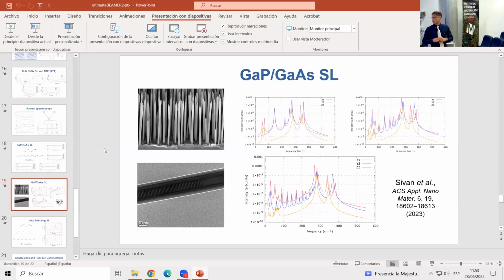And what about the intensity of the Raman peaks? The intensity of the Raman peaks, I guess that I sort of cheated, meaning that we can only assess that afterwards. So only after having computed the spectrum, we observe that actually in the twinning superlattice case, the superlattice structure only affected the Raman spectra in a minor way. Because in principle, of course, you will expect a more homogeneous electronic density along the lattice, because basically electrons are facing the same amount of charge in the nuclei. But electrons are so strange and quantum and unpredictable that you can only assess what is going to happen once you have computed the full wave function, whatever the approximation you use, and you have computed the full electro-optical response of the system for the twinning superlattice.